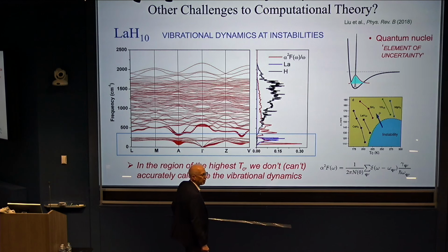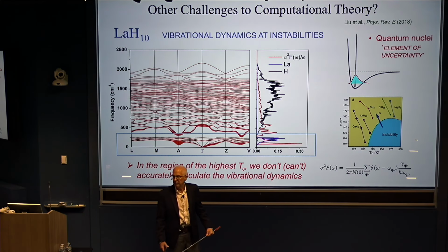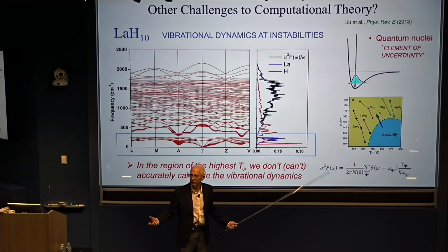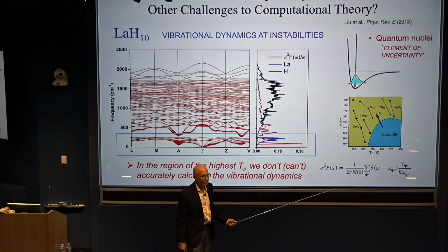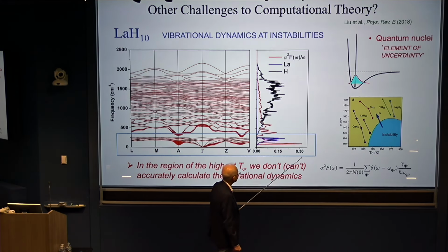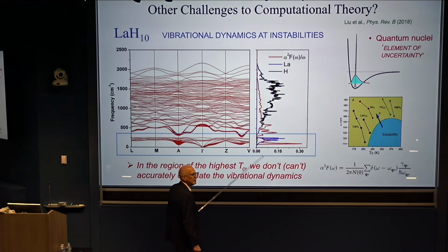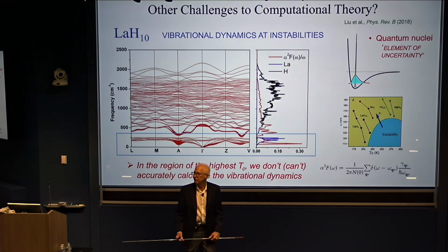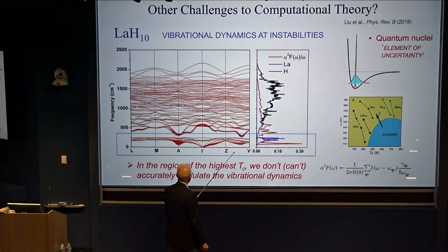When they're close to zero, you're in an anharmonic regime. In some cases, it may be not bound. It may be diffusive. But in order to do the calculation, we have to use the harmonic approximation, which is clearly problematic. So just in the region where we want to get an accurate prediction of what TC is, we really don't have the tools necessary to do that. So this is another challenge for theory. So all the action really is right here, where the hydrogens are very, very close to having basically a zero bound state. They're not in a harmonic well.